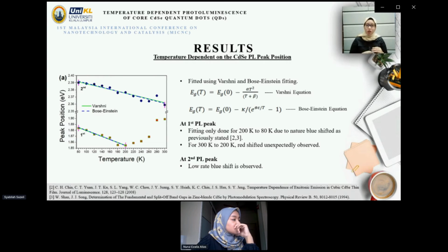When the Einstein temperature value is lower than the optical or LO phonon energy, acoustic phonon will highly contribute to narrowing the bandgap because of the electron-phonon interaction. From this study, it is expected that the acoustic and LO phonon highly contribute toward the quantum dot bandgap shrinkage, as our Einstein temperature recorded is lower than LO phonon for the first PLP. However, for the second PLP, the parameter recorded is far from previously reported.